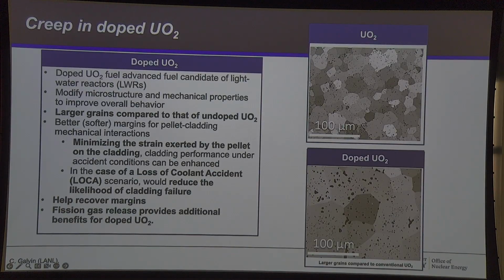Also quickly wanted to say, I also mentioned doped UO2. The real reason why you dope UO2 is that during the manufacturing, your grain size increases. That has benefits. And one of the benefits is better mechanical properties. The fuel is a little softer. That matters because when it pushes against the cladding, the fuel doesn't push quite as hard because it deforms a little bit itself.